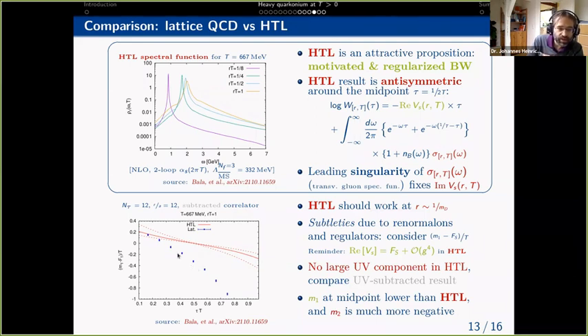And we compare here the lattice data in blue to the prediction by hard thermal loop, where in both cases we've subtracted the singlet free energy in order to get rid of some issues which pertain to the fact that both of these quantities are affected by renormalons and have a divergence on the lattice. So what you see is that the hard thermal loop result has an anti-symmetry around the midpoint, which we do not see in the lattice result. Therefore, if we want to analyze the lattice result in terms of this hard thermal loop idea, we have to restrict ourselves to a very, very narrow range around the midpoint where results might still be consistent with this anti-symmetric condition that we have for the hard thermal loop result.